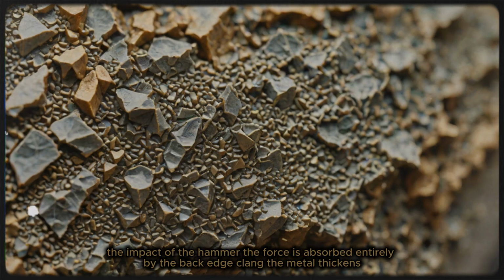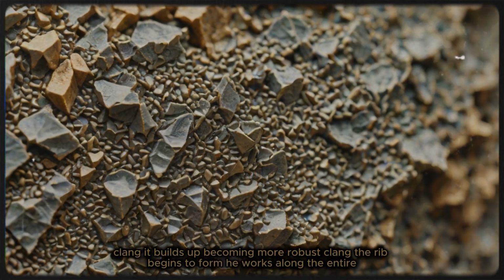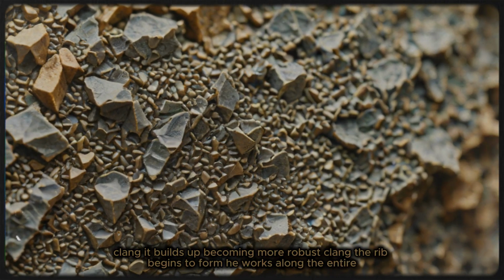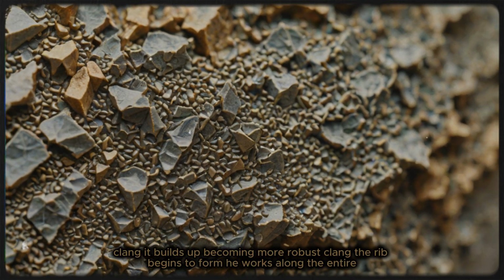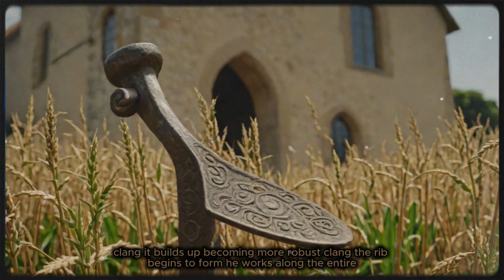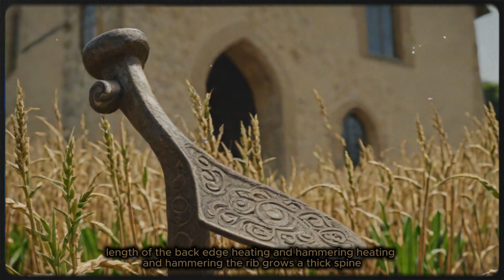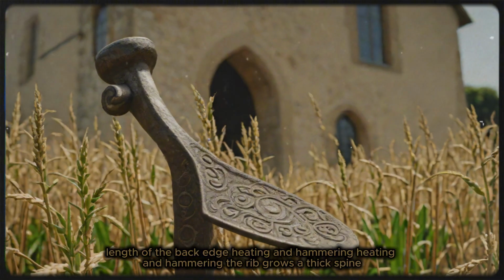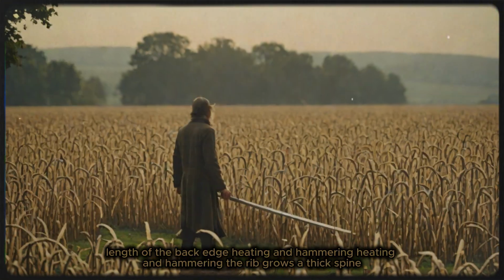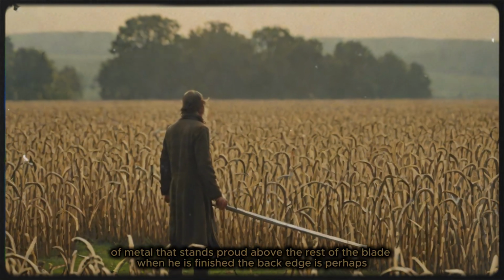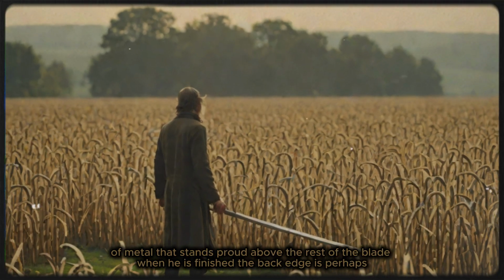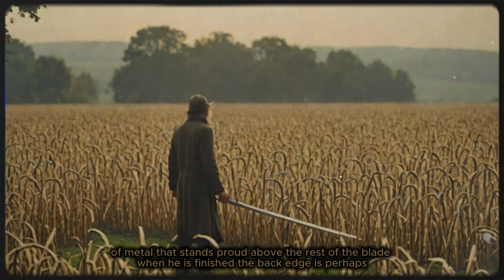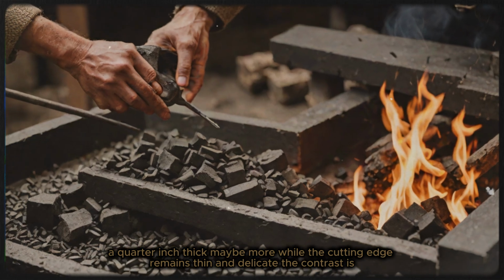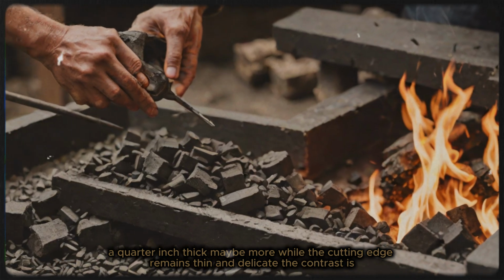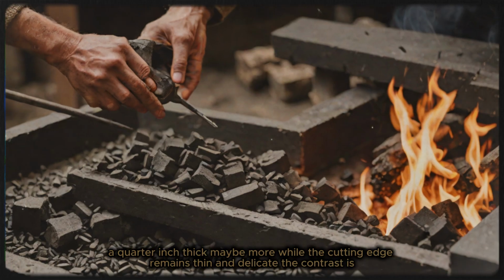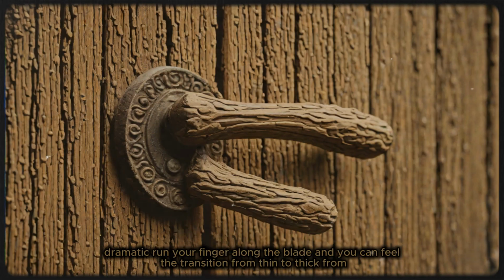Clang. The metal thickens. Clang. It builds up, becoming more robust. Clang. The rib begins to form. He works along the entire length of the back edge, heating and hammering, heating and hammering. The rib grows, a thick spine of metal that stands proud above the rest of the blade. When he is finished, the back edge is perhaps a quarter-inch thick, maybe more, while the cutting edge remains thin and delicate. The contrast is dramatic.